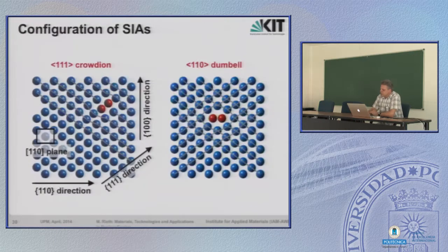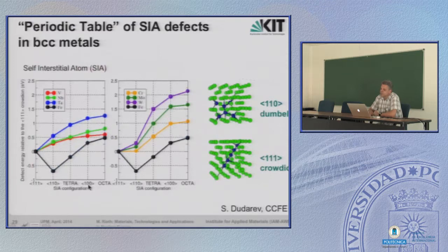If you can view this with one blink of an eye, maybe this is easier to catch. If we have a look at a BCC lattice, and this is the 1-1-1 direction of the atoms, and you squeeze here instead of one atom, two in this row, this is what we call a crowdion. That's in the 1-1-1 direction. So here, one of those two atoms is a self-interstitial atom called a crowdion. If you place it here, slightly shifted in the 1-1-0 direction, then it is called a dumbbell. So in principle, you have the choice, but not only this. As I said, you could put them in a 1-0-0 plane or in an octahedral place or tetrahedral place.